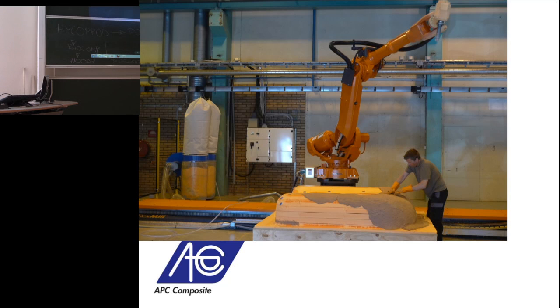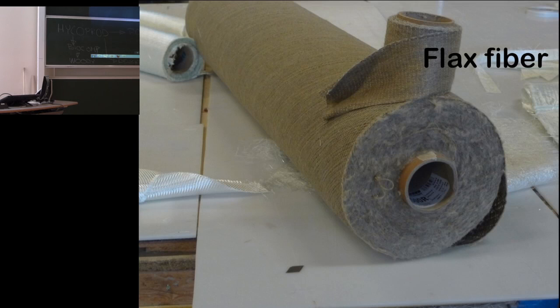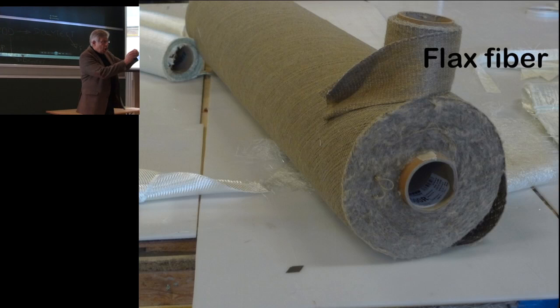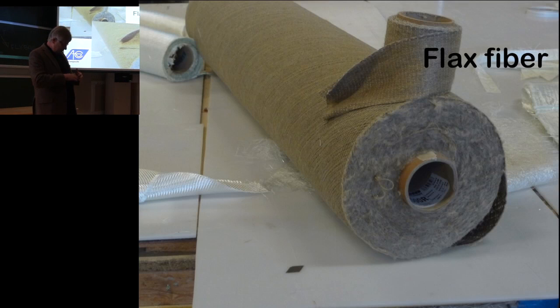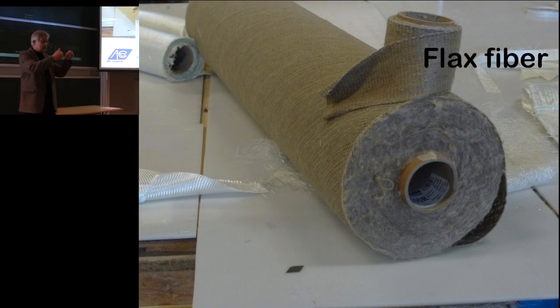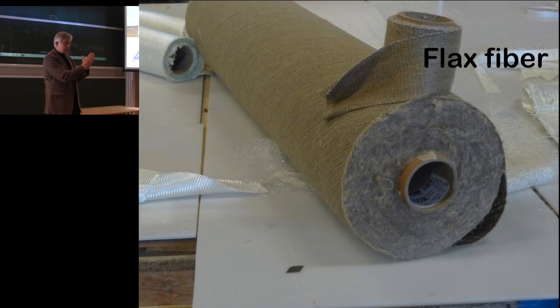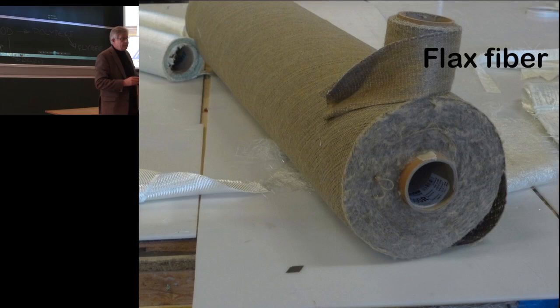Yes, good. And meanwhile, I called a friend down in Poland who grows flax fibers. I said, I need 1.5 ton of flax fibers. You know, when you have a suit or something in flax, it's hard twisted yarns, like you weave with, to get good mechanical properties of the cloth. But when I want to make a composite, I don't want hard twisted yarns, because I want to wet the single fibers in the yarn. So I glue the single fibers to each other. So I wanted very soft twisted yarns. So I had to try to do that. And that 1.5 ton was sent to a colleague in Italy, Claudia Canal at Selcom, outside Venice, and asked her to make